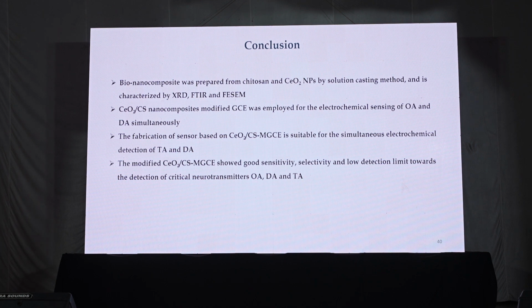The cerium dioxide nanoparticle modified glassy carbon electrodes were employed for the electrochemical detection of octopamine, tyramine and dopamine simultaneously, and there was no interference. The fabricated sensor is used for the simultaneous electrochemical detection of tyramine and dopamine, and the modified glassy carbon electrode showed very good sensitivity, selectivity and low detection limit towards the neurotransmitters octopamine, dopamine and tyramine.